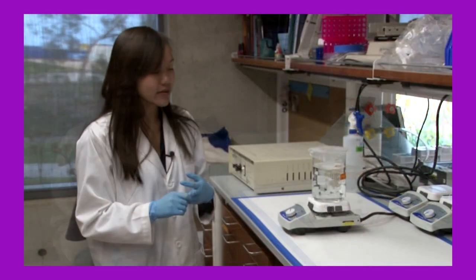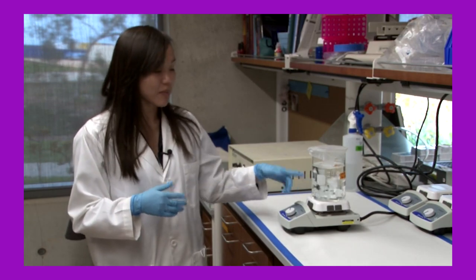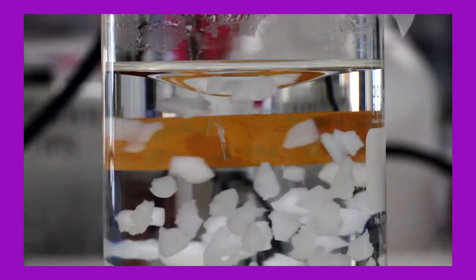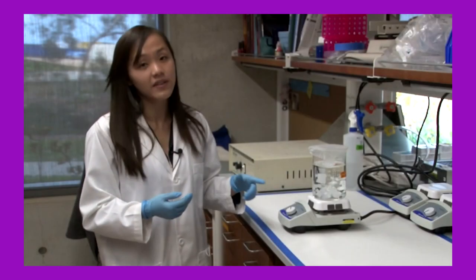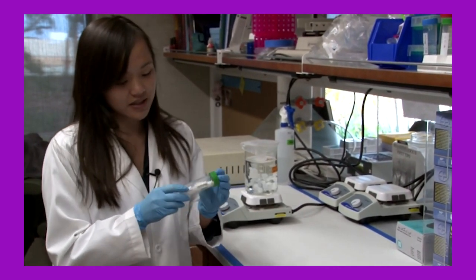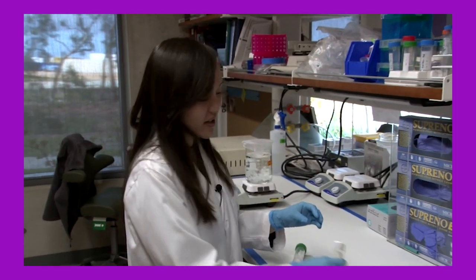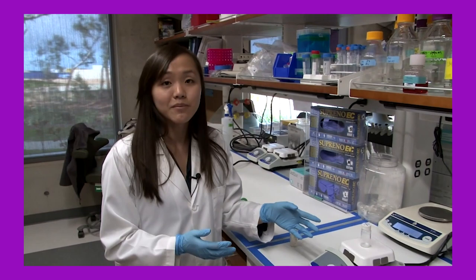So how did they do it? Before we get to that, let's go over the procedure of how they actually attain this ECM hydrogel. It first involves chopping up heart tissue — in this paper, they take it from pig hearts. The first step is chopping it into tiny pieces, putting it into a beaker, and stirring it up with detergent to remove all the cellular contents. After a couple of days, they rinse it to remove the detergents, leaving just the structural proteins that make up the tissue. That is then freeze-dried into a styrofoam-like substance — really light and crispy — and milled into a fine powder, which is then digested with an enzyme to liquefy it.